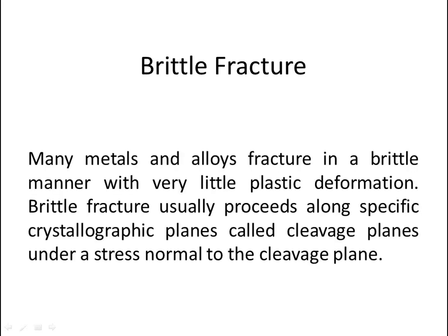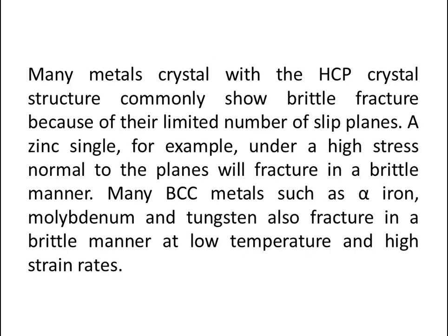Let's talk about brittle fracture. Many metals and alloys fracture in a brittle manner with very little plastic deformation. Brittle fracture usually proceeds along specific crystallographic planes called cleavage planes, under stress normal to the cleavage plane. Many metals with the HCP crystal structure commonly show brittle fracture because of their limited number of slip planes. A zinc single crystal, for example, under high stress normal to the planes will fracture in a brittle manner. Many BCC metals such as alpha iron, molybdenum, and tungsten also fracture in a brittle manner at low temperature and high strain rates.